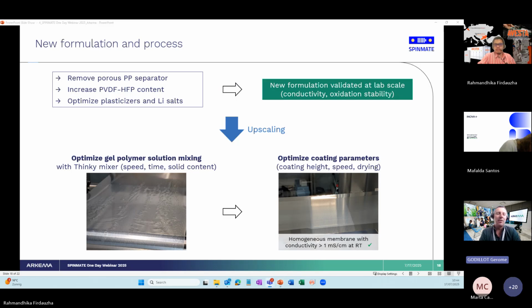So what we did to counter this removal of the PP separator is to increase the PVDF content, and then we also had to change and optimize again the plasticizer and lithium salt to get sufficient conductivity. So this is the work we have done at lab scale too. We started again at lab scale, and we managed to get a formulation with higher PVDF content and a different plasticizer and lithium salt that allowed us to reach good conductivity.